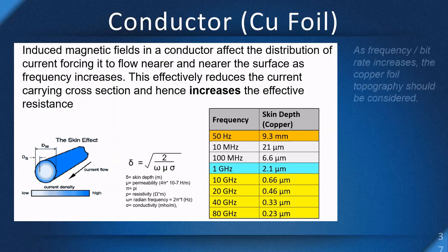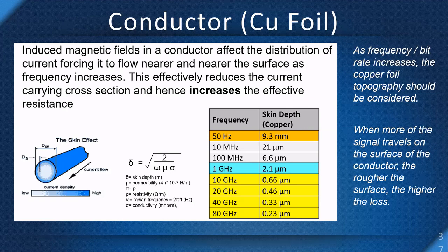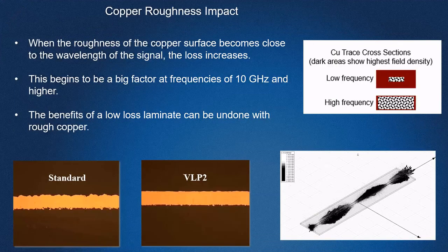So copper foil becomes important for high frequency signals, just like the dielectric, just like the loss tangent of the materials. As frequencies go up, I'm sure most people are familiar that it pushes the energy into the surface of the copper. We call it skin effect, and that's where we want smoother copper foils for high frequency circuits. For things like FR4, it's not critical, but when you start going into lower loss materials, you want to make sure you use a smoother copper. Again, this is something that we work closely with fabricators on. It becomes a big factor as you go higher in speeds above 10 gigahertz.